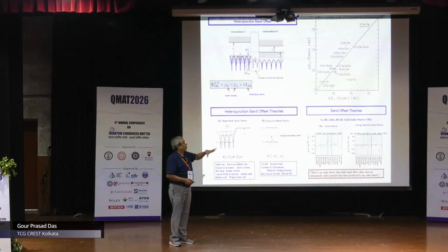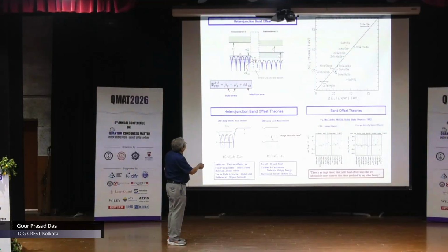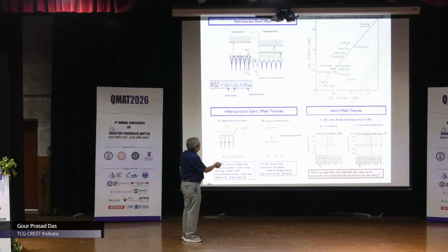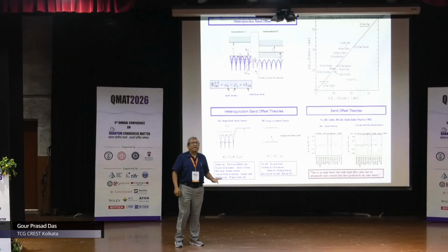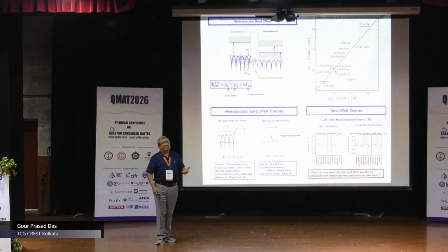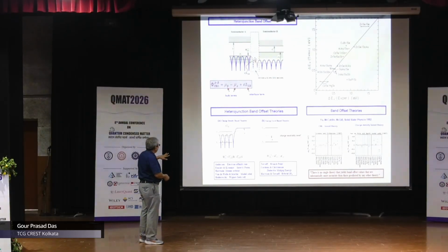Now, at least 100 to 200 papers have come out on this, and I have just summarized it. Let me show you one picture here. This is the valence band offset obtained by density functional theory, and this is the experiment. Okay, and look, almost all the dots fall on the 45-degree line, which means the density functional results match the experimental result pretty well, excepting there are some bad boys of the game, like for example gallium phosphide silicon or zinc selenide germanium and things like that. But otherwise it almost all falls on this 45-degree line, which shows that DFT really is successful for predicting the band offset in epitaxial semiconductor heterojunctions. Okay, the other details are there, and these are all available in the literature.